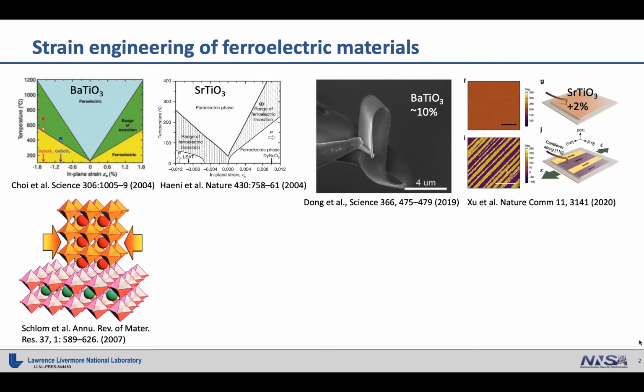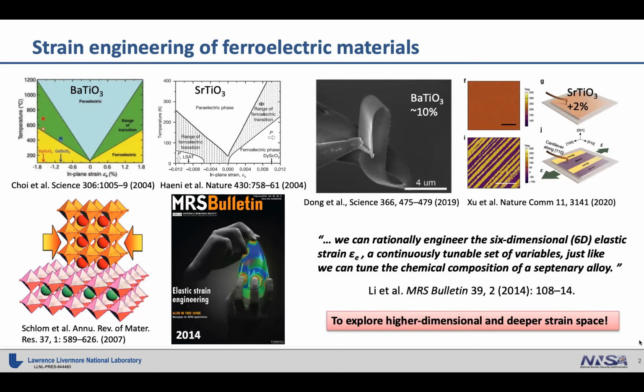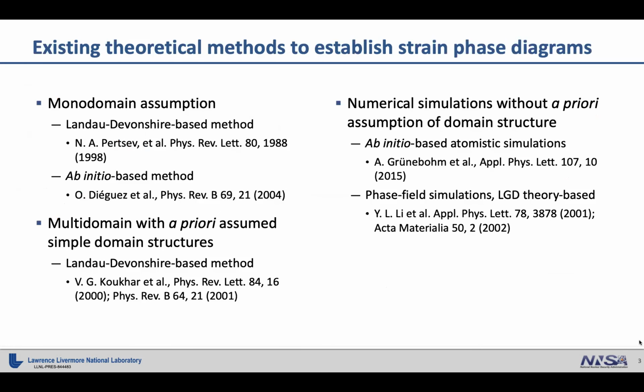In recent years, there's a growing interest in fabricating freestanding ferroelectric membranes, which are substrate-free and allow you to apply huge mechanical deformation as well as more complex strain states to these materials. I would like to quote one remark from an editorial paper from Professor Li at MIT, where he said that we can rationally engineer the 6-dimensional elastic strain, which is a continuously tunable set of variables, just like we can do with the chemical composition of a septenary alloy. So there's plenty of room in the strain space that we can explore to activate more unprecedented properties in ferroelectric materials.